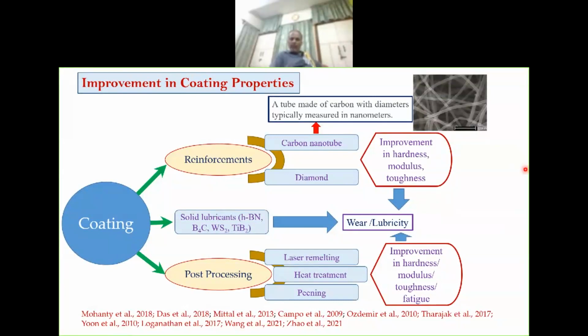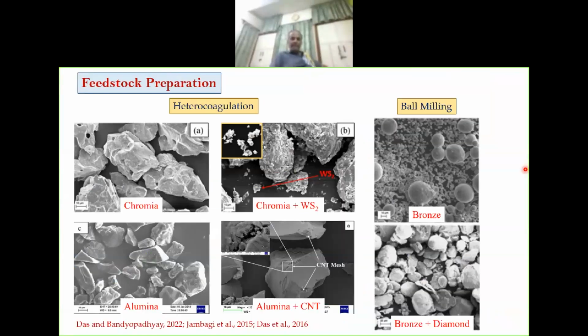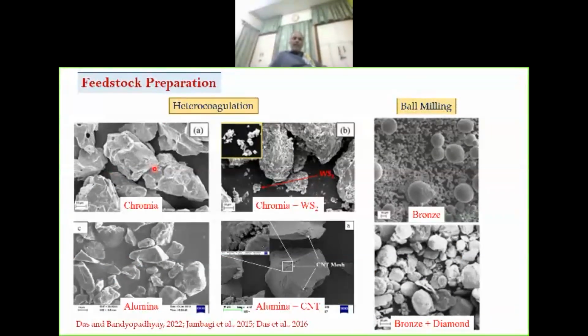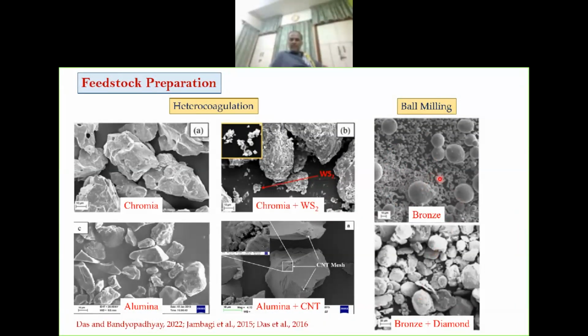Okay. Now there are some issues here that I'll briefly address. First, if you want to have a lubricating coating, add tungsten sulfide. You want to improve the hardness with bronze, we use diamond; bronze and diamond mix well. You want to have improvement in wear properties of alumina, mix CNT.